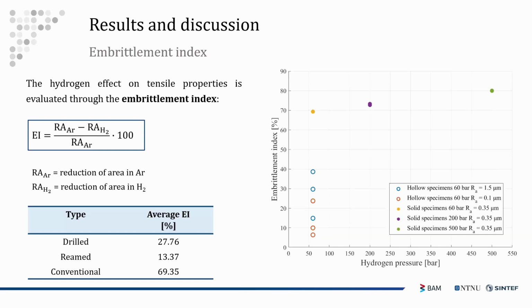As you can see from the table in the bottom part of the slide, the drilled specimen have a relatively higher, well, a higher average embrittlement index compared to the reamed specimen. So apparently the surface roughness has a substantial impact on the hydrogen embrittlement susceptibility.